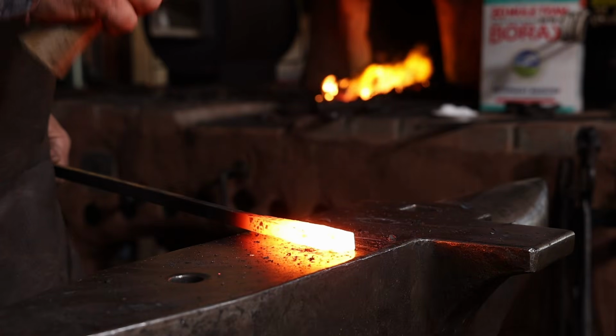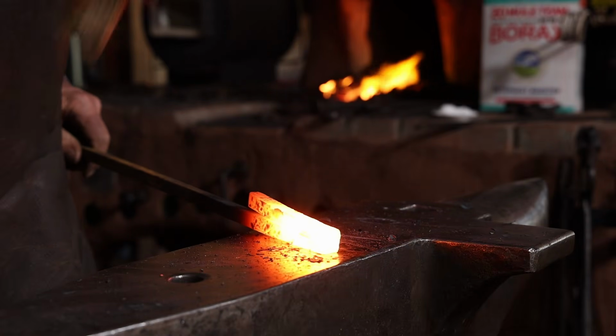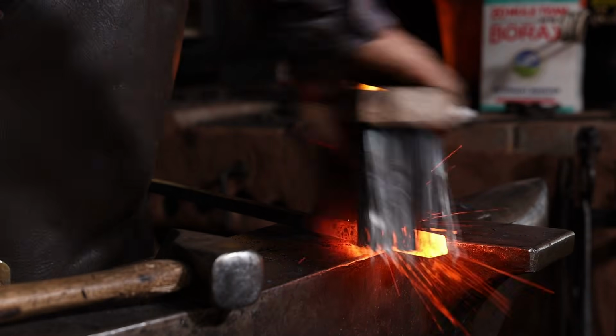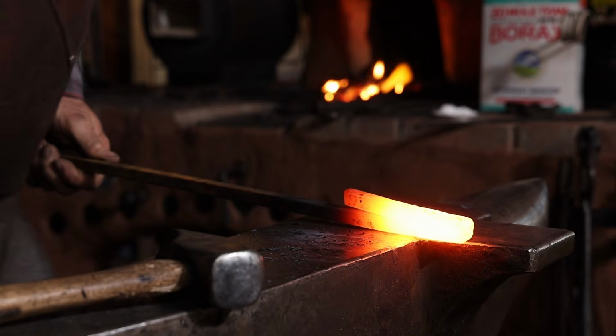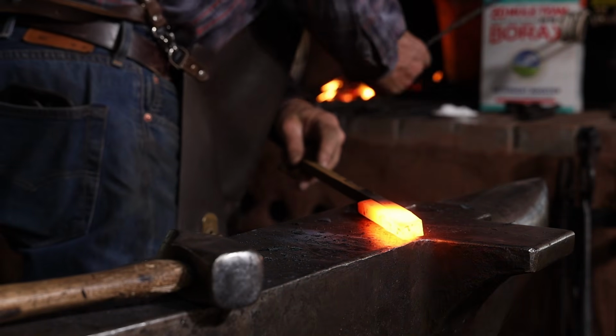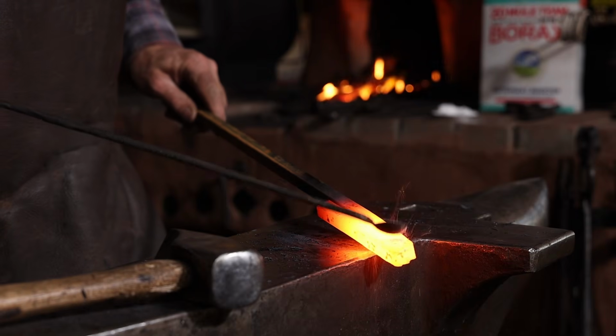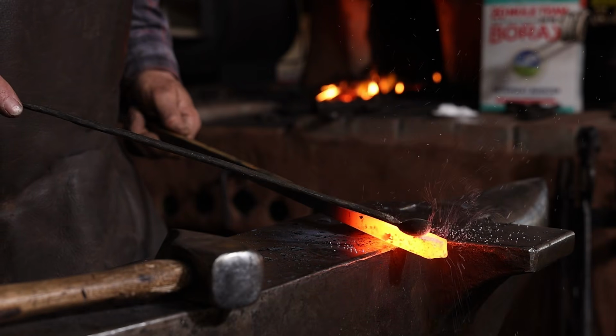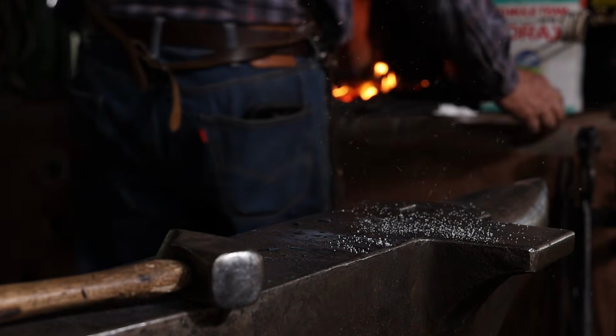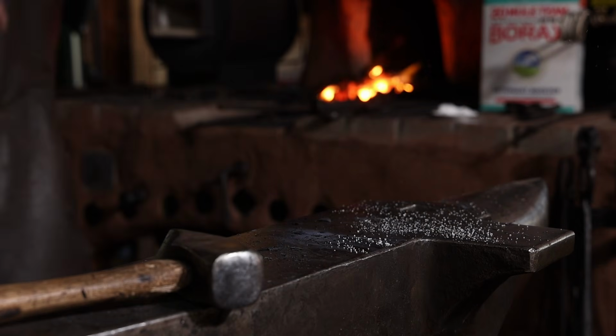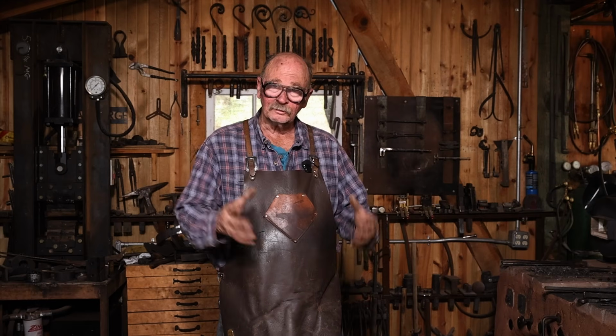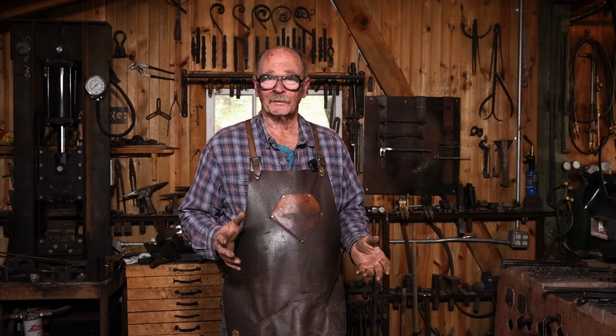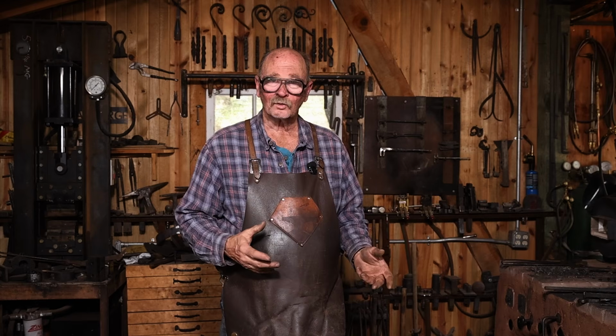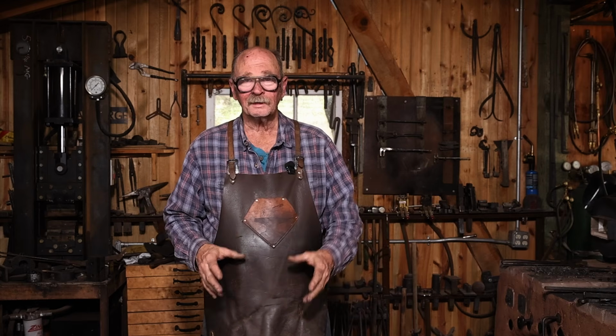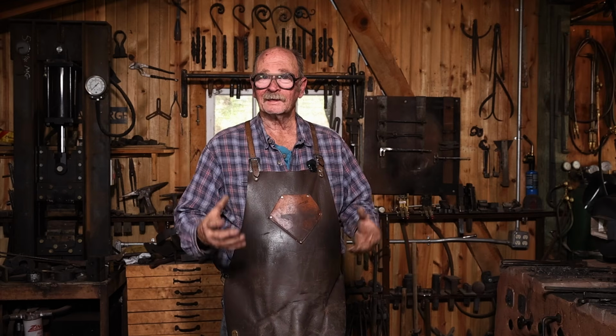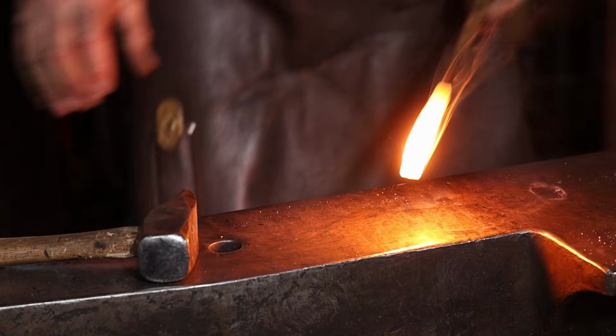If you think you've got the weld, it's okay to refine the joint a little bit, but if you're not sure, it pays to wire brush it lightly. Put a little bit more flux on it, and then go back to the fire. If the weld is not completely stuck and you're losing your welding heat, there is no reason to keep hammering on it. Get it back in the fire, take another welding heat, and then finish getting the weld. If the weld is stuck, you can start refining it as it cools off. Again, we're looking for that bright orange to lemon yellow.